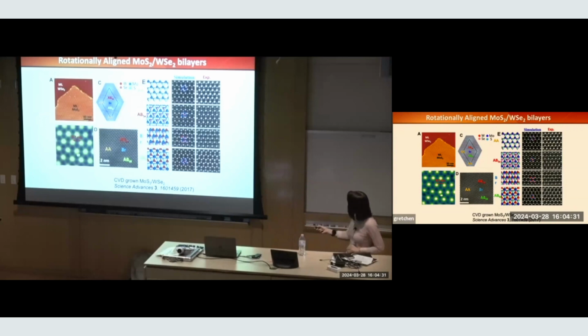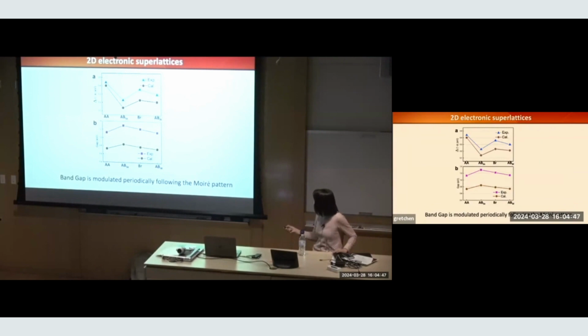Okay, so these are how Moiré patterns form. You can measure them with different tools. This is STM. This is STEM. Simulation, experiment. Everybody knows that these Moiré superlattices exist. And now I can measure their local band structure. Let me just focus on this. So these are the few high symmetry points, right, with slightly different atomic alignment. And this is the measurement. You can see from one location to the other, the local band gap changes by 200 meV. That's quite sizable compared to the total band gap. And here's a calculation. The calculation is off.